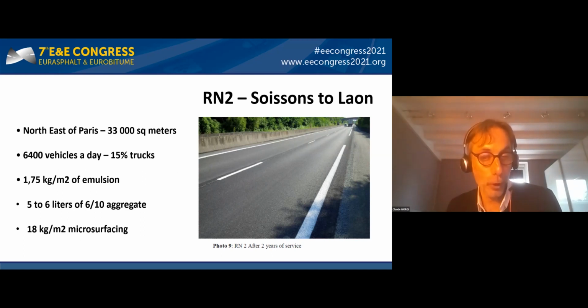33,000 square meters were applied on the RN2. The traffic was very heavy, more than 6,000 vehicles per day, 15% of which were heavy trucks. We then adapted the dosages to this traffic and applied a surface dressing consisting of 1.75 kilograms per square meter of emulsion and 5 to 6 liters per square meter of a 6/10 aggregate.